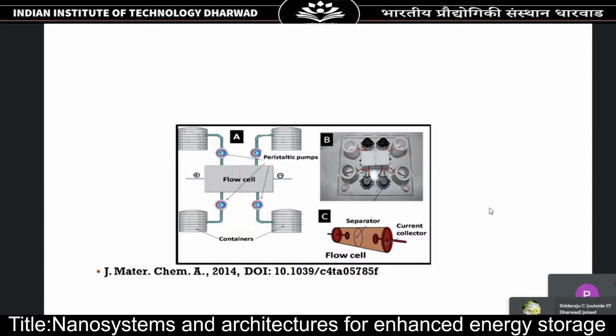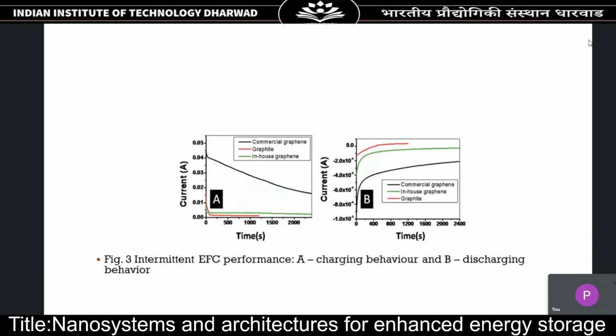So this was a device which was made, and it was used for testing the electrochemical flow cell. You can look at the chronoamperometry curves, which is current versus time. You can see that the commercial graphene is performing much better than graphite or in-house graphene. And similarly, you can also see the discharging behavior. Again, the graphite discharging is not as good as if you take the commercial graphene or the in-house graphene.